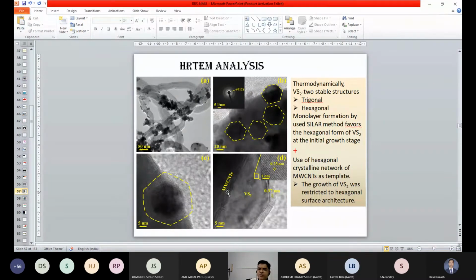So basically this vanadium sulfide has two stable structures. One is called the trigonal structure and the second one is the hexagonal structure. As we used the SILAR method, that is monolayer formation, where cations and anions are controlled at the ionic level so that vanadium reacts with the sulfur, there is a formation of a monolayer in one SILAR cycle. And if you repeat that SILAR cycle, the growth of the particle can be enhanced, meaning you can control it at the monolayer level.